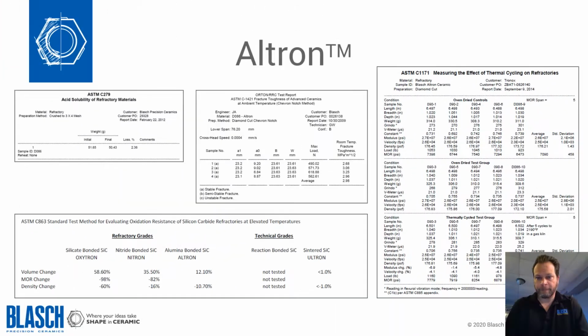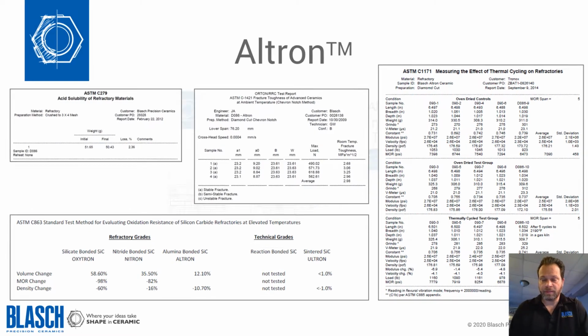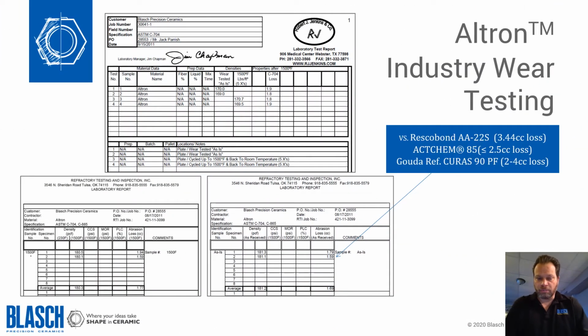application. We further analyzed the material to make sure that it was suitable for a cat cracking unit. We measured the thermal shock resistance by cycling it. We measured the acid solubility, the oxidation resistance, and a host of other tests were performed on the material. One of the most important features touched on previously was the abrasion resistance. And although we have our own in-house C704 tester, most clients wanted it to be approved and tested by independent labs, such as the ones listed here.